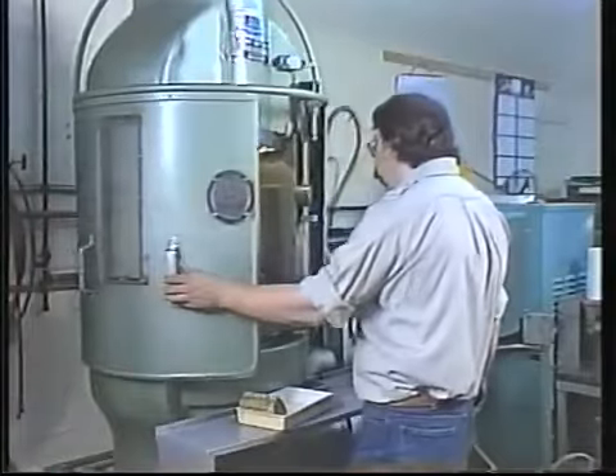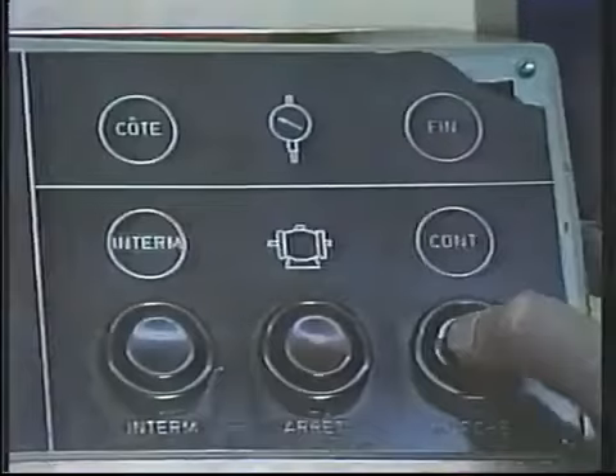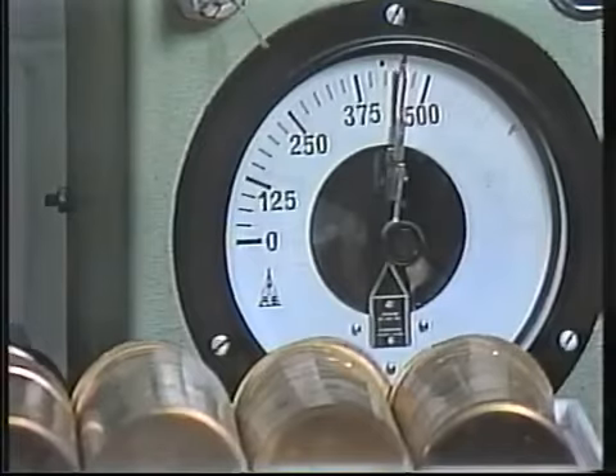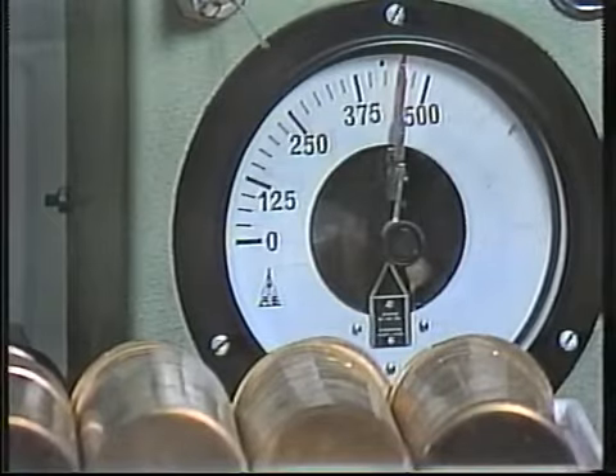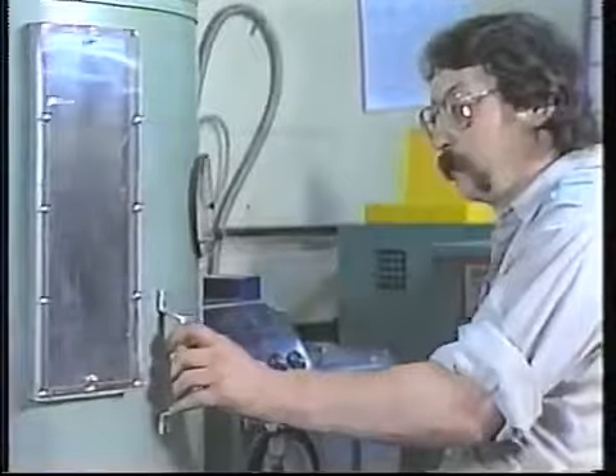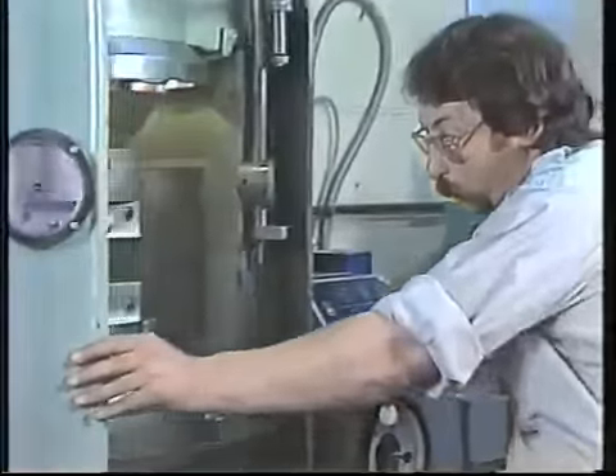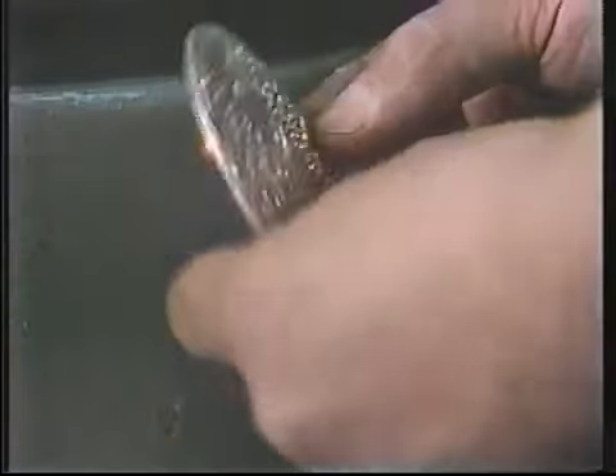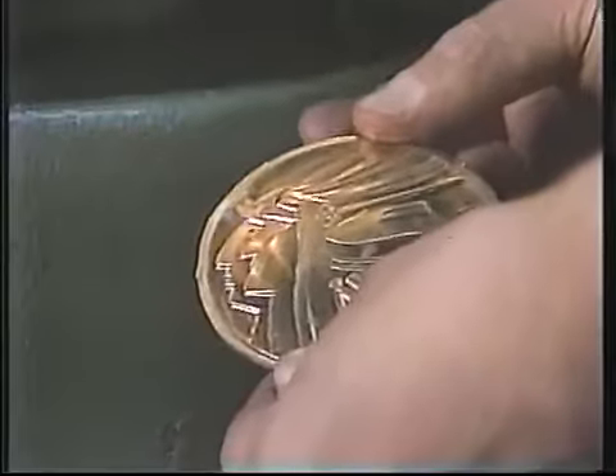The blanks are cleaned prior to inserting them into the die. The press is now operating at 475 metric tons, which will yield a tonnage of approximately 1 million pounds. The metal tends to stick slightly and the top die is removed with a slight tapping.